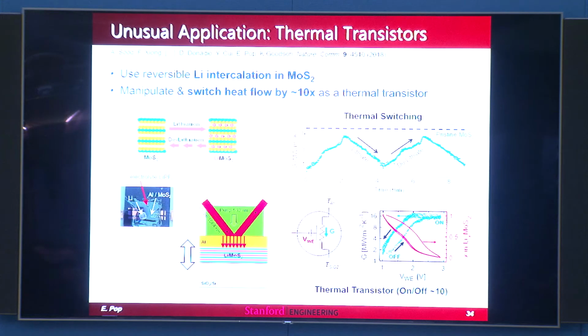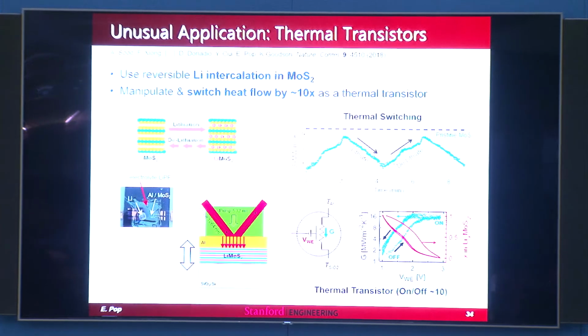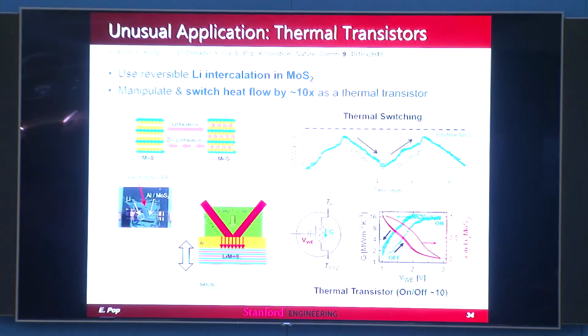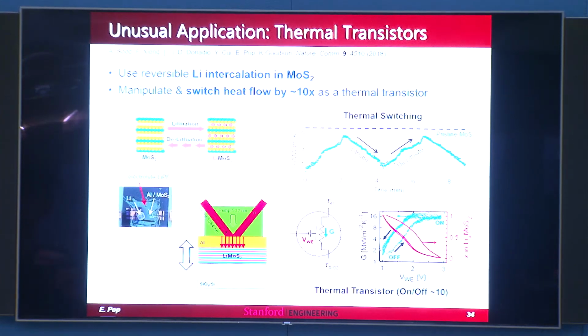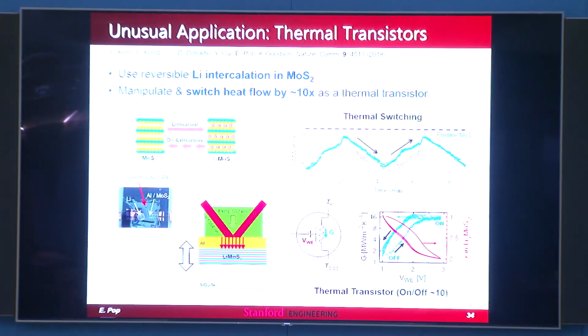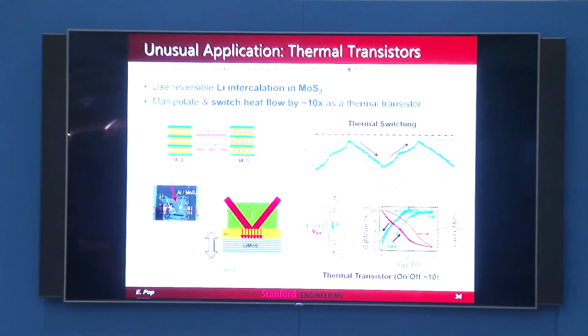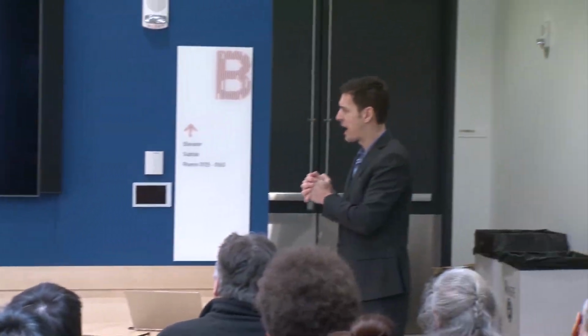You can actually see these thermal maps of the device, and you can map the lithiation of the device as the lithium moves in. And it's not a super fast process, unfortunately. But there are ways to speed it up. It's just naturally not a very fast process. But we can actually see this in real time. I think there's a movie of that in the supplementary part of the paper. You can control this.